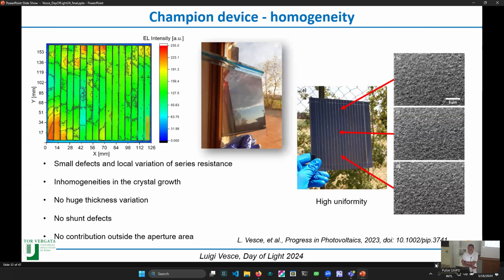At the end, we put all together this improvement in one module, and then first we check the electroluminescence. Here you can see that you have some small defects. There is some resistance, still you have some variation, but not so huge. You have some inhomogeneities, okay, but there is not a huge thickness variation, not any shunt defects that you cannot see, for example. And this is good for the measurement.